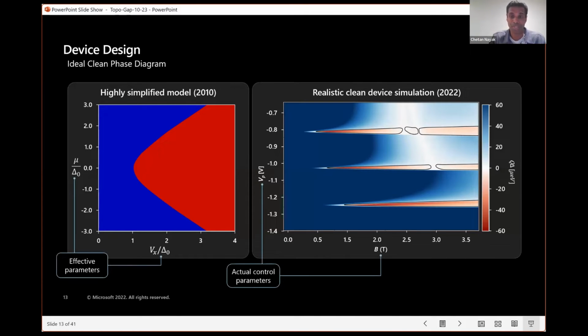You'll also note, another important point here is that these are the actual control parameters of the device, whereas over here, this was an effective parameter, which is the chemical potential, and the Zeeman energy. Here, we're talking about the actual plunger gate voltage, and how it affects the chemical potential depends on the lever arm, so it depends on screening and the geometry of the device. Over here, there's the magnetic field, and how much Zeeman energy depends on the g factor, which is normalized by the coupling between the semiconductor and the superconductor. So these are actual control parameters that you could compare directly to the parameters you control on an experiment.